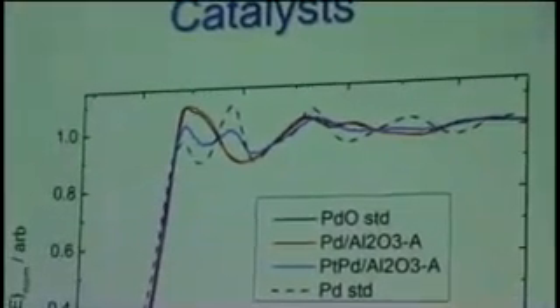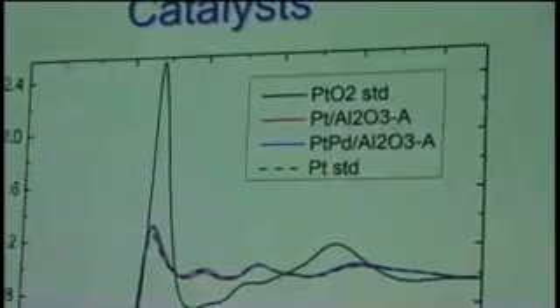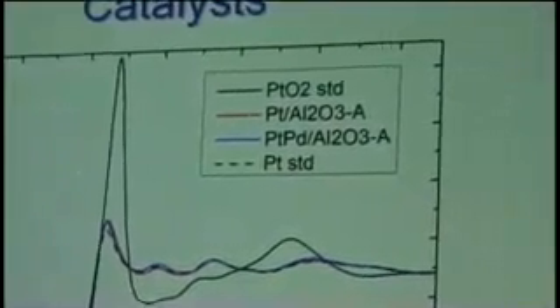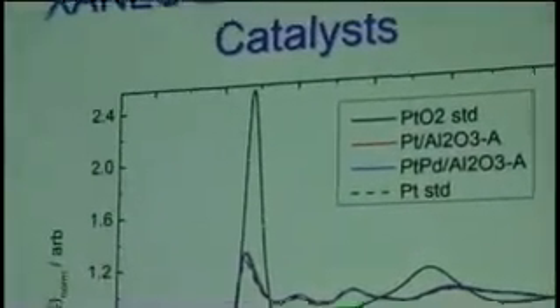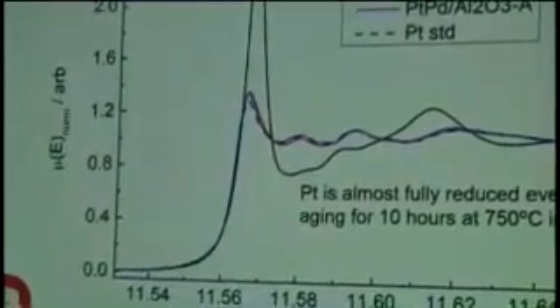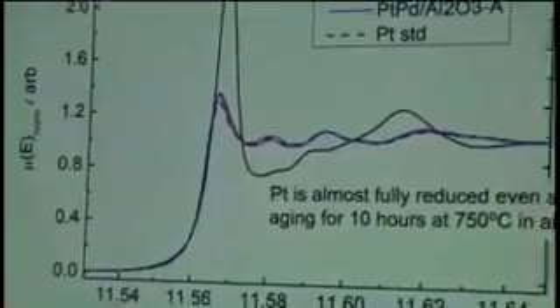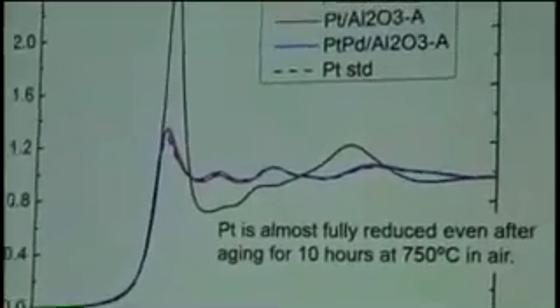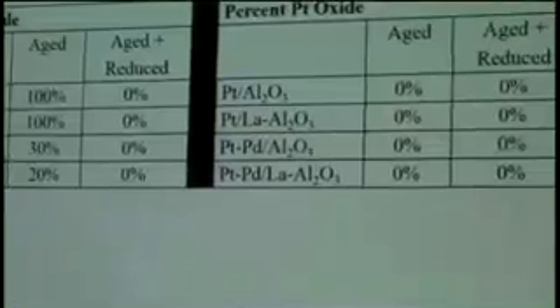It matches the oxide, so hardly any reduced palladium at all. If I take platinum, on the other hand, it is the platinum standard. Aging in air is all metallic. So aging platinum gives you only platinum metal in air at 750.